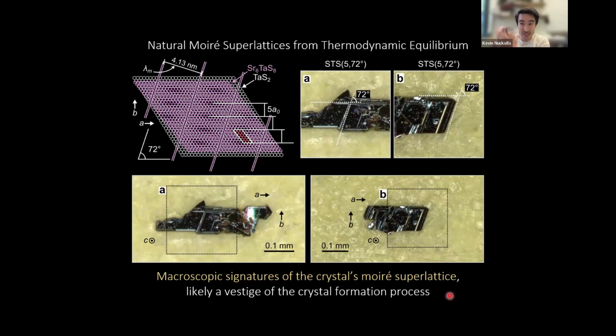This is highly unintuitive to me as someone who made twisted bilayer graphene devices, where if you warm them up a little bit, oftentimes they just relax and they reduce their Moiré superlattice. But this suggests that in bulk Moiré materials, the Moiré superlattice can not only offer a competitive energy scale for crystal formation, but in some situations, it's a candidate for the dominant energy scale for stabilizing this compound. Yeah, really beautifully unintuitive. I don't understand why this is the case, but for STS-5 and STS-13, this is basically always the case. Every crystal looks like this.